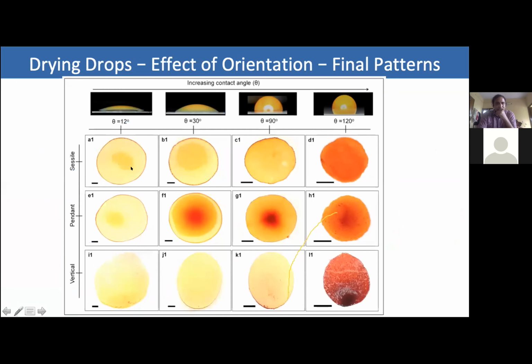Okay. These are some microscopy images of the drops dried in sessile, pendant, and vertical configurations, and different substrate wettabilities. Theta is equal to 12 all the way up to 120. Most of the studies to date, even when they have done different configurations, were done with hydrophilic substrates where the contact angle is very low. In such cases, you don't find subtle differences in the deposit patterns. However, when you look at the effect of contact angle, you can clearly see that the deposit patterns are very, very different. If you take a contact angle of 90, you get a coffee ring in sessile mode, a central dome in the pendant drop mode, and a deposition at the advancing side in the case of vertical drops.